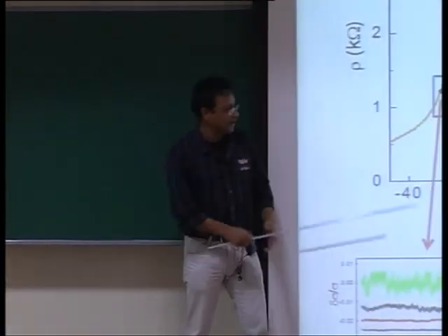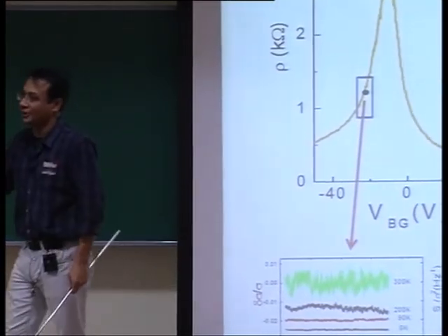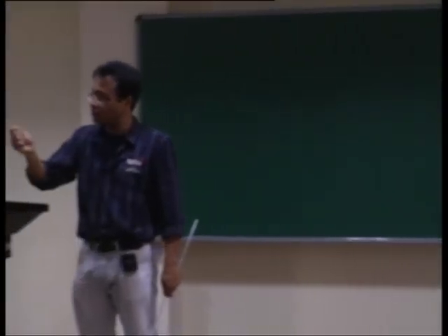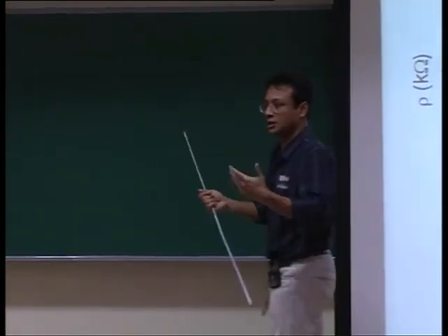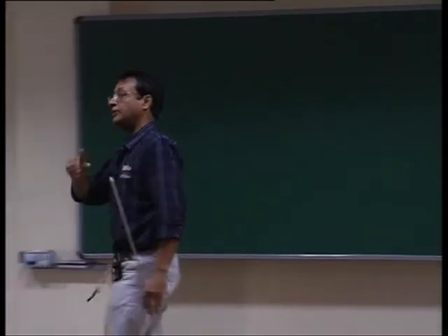You're absolutely right. You see, there are two ways we do the experiment. One is simply looking at the sweeping of gate voltage, and if you look at that, then there's no problem. As you change the gate voltage, you can see this fluctuation magnitude increases with decreasing temperature, which is supposed to be the case in a quantum effect. Fine. This is one of the ways.